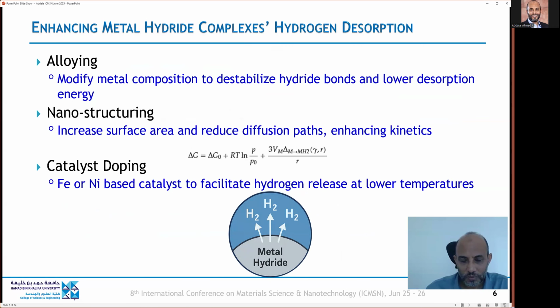To enhance the performance on the release side, there are usually multiple approaches. One is alloying, where you change the metal composition to make a less stable hydride bond, and that lowers the desorption energy and the temperature for the release. Another viable approach is nanostructuring, by making the metal hydride a smaller size, which increases the surface area, reduces the diffusion pathway, and enhances both the kinetics and the release temperature, because again the free energy for the equilibrium between the hydride form and the hydrogen-free form depends on the size of the metal hydride.